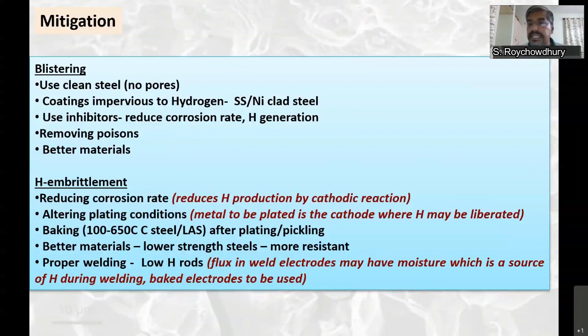If you're talking about steel, martensite is one high hardness phase. If a lot of martensite is present, then the steel is very hard and it has very, very poor resistance to hydrogen embrittlement. Or if it is very soft, with a ferrite pearlite microstructure, then it will have higher resistance to hydrogen embrittlement. Again, reduce corrosion rate. Altering plating conditions: in electroplating, the material to be plated is made the cathode, where hydrogen evolves. So altering plating conditions can minimize this hydrogen evolution and hydrogen pickup.